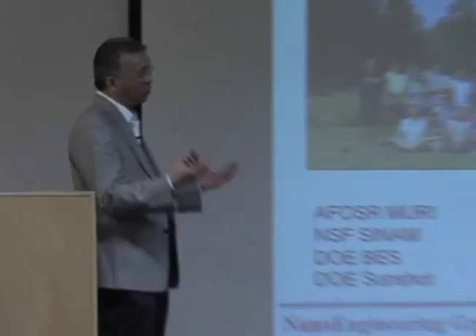So a general question on your heat transfer: you showed silica having higher heat transfer than between 2 gold spheres. Is that in general true because of the emissivity of gold or something, or why is that? Well, in this case, first the metal emissivity is small, right? And also one could argue, why don't you work in the surface plasma regime? But the surface plasma of the metal is typically at very short wavelengths. So for the glass, the wavelength is about 10 micron, 8 micron regime, which is actually just right for the thermal emission. So that's generally the case most of the time when we work on those polar materials, even gallium nitride. They should all have similar phenomena. It's just we haven't done this experiment.